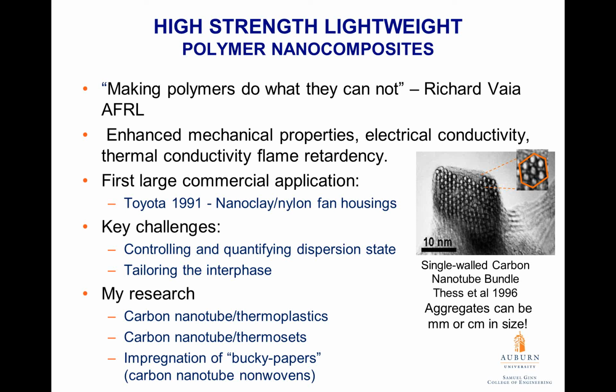Now, single-walled carbon nanotubes, shown here, are probably the most notorious because trying to break up this bundle that comes out of this reactor takes several orders of magnitude more than thermal energy. So you have to do it using thermodynamics, a subject that most of you probably recall from school. Each one of these little circles here is a 1 nanometer diameter nanotube, but these aggregates can actually be millimeters or centimeters in size, in which case they're not going to enhance mechanical strength. They're actually just going to create stress risers and deteriorate mechanical strength.